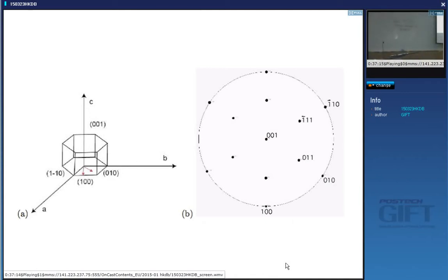So in the hexagonal system, if you use the three index notation, that means X, Y, and Z, then you will get different indices even though they are crystallographically equivalent planes or directions. So how do we solve this? Four index notation. Have you come across that? Yeah. Now in the case of planes, it's very easy. So we have HKL as the three index notation. We simply make it HKIL, where I is equal to minus (H plus K). Okay. So 100 becomes 10 bar 10, right? What does 010 become?